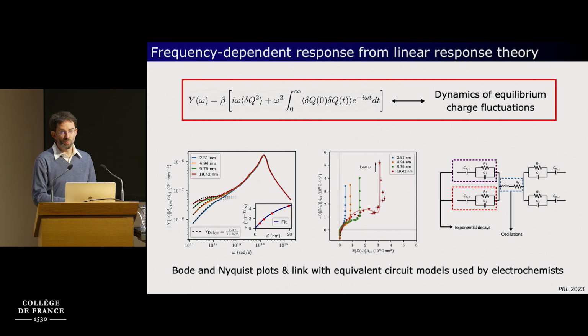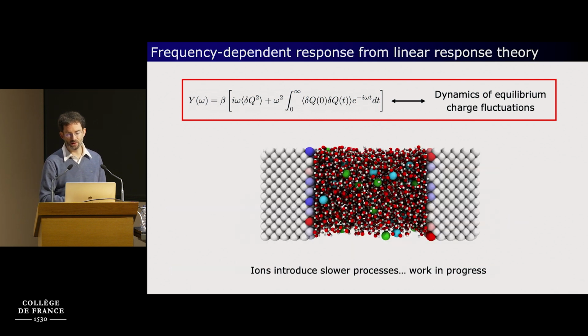Of course, the case of pure water is interesting, but there are essential features that we miss with the kind of models that we use, related, for example, to Grotthuss mechanism and proton transfers that were discussed by Misha. But there are interesting features associated with the presence of ions that we are now investigating, in particular at lower frequencies. I'm not going to describe that, but you really have a tool now to correlate the frequency-dependent electric response to microscopic mechanisms, both for charge transport in the bulk liquid, but also for what happens at the interface.